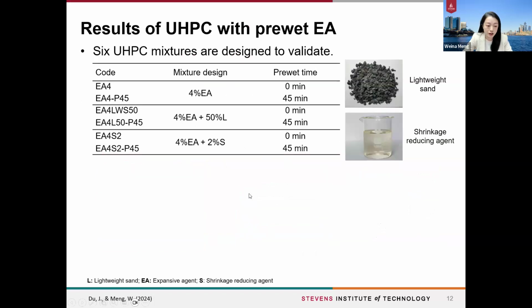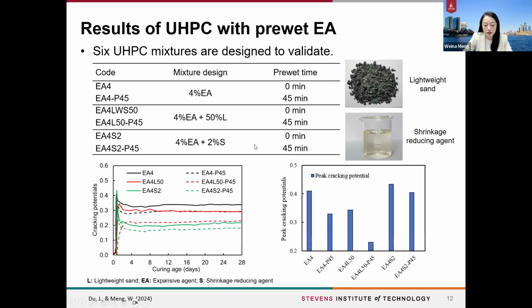Here we compare three groups of UHPC mixtures with different shrinkage reducing strategies. But for each of the strategies, we all use the expansive agent, and we compare the case with and without the pre-wetting method. The result shows that with the pre-wetting, we can significantly reduce the peak cracking potentials as well as the cumulative cracking potentials. So that's for the best mixtures with a 4% expansive agent, 50% internal curing agents, the lightweight sand, and some 45 minutes of pre-wetting. We have the mixtures until now didn't see any cracks.